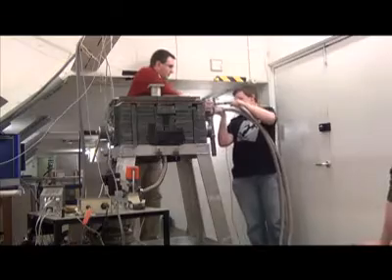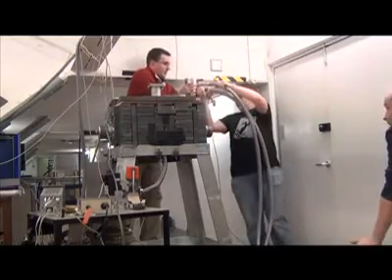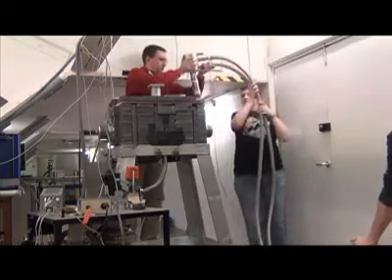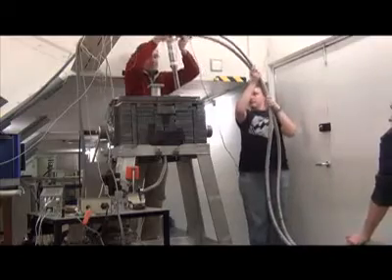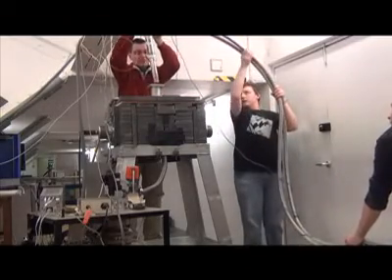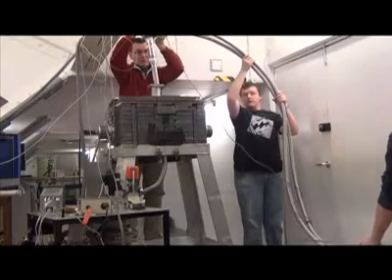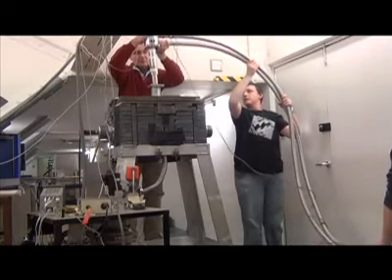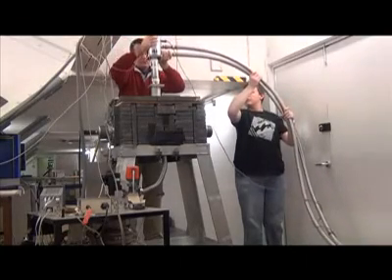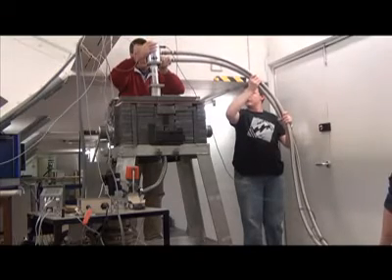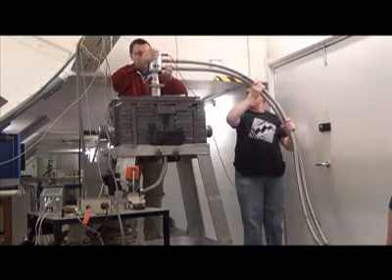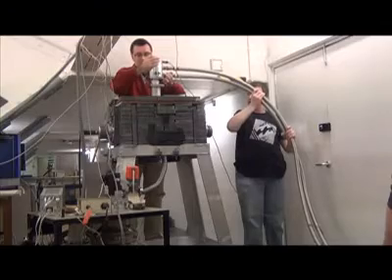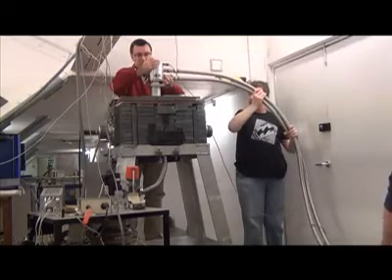In general, samples can be measured at a range of temperatures with the current spectrometer fitted with a cryocooler capable of reaching 4 Kelvin. The positron source is located at the end of a source rod which extends from the left hand side of the sample chamber. The annihilation gammas enter through holes on the front and back side of the sample chamber. One of the detectors can be seen towards the end of the lab in the distance.